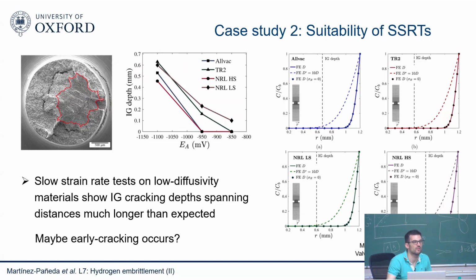So depending on the geometry of the specimen and what the material diffusivity is, you have not reached steady state in that. Exactly. But in these nickel alloys, they try to make the samples small, but you still need millimeters. You need to grip them and so on. You cannot do tiny samples. So for steady state in these nickel alloys, you may have to wait a couple of months or something. It's very low diffusivity, 10 to the minus 14 and so on. So people still do the test, and they see a lot of embrittlement.